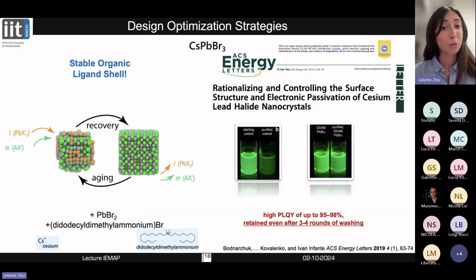So for recovering the optical properties of perovskite quantum dots, the computational work proposed to add lead bromide salts and also a more stable ligand shell, by replacing this cesium here, for example, with a quaternary ammonium organic ligand. And in the experiments, this led to boosting the photoluminescence quantum yields to nearly unity. And most importantly, that was retained even after several rounds of washing.